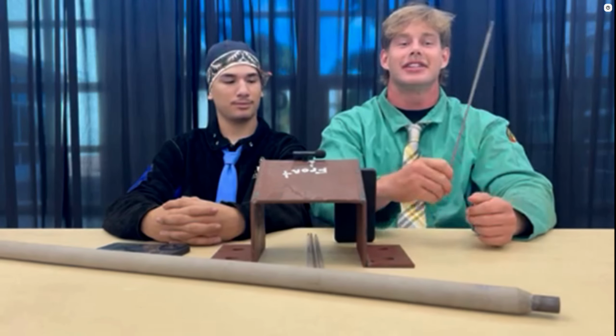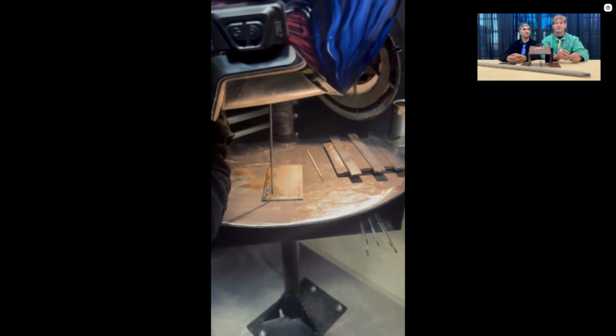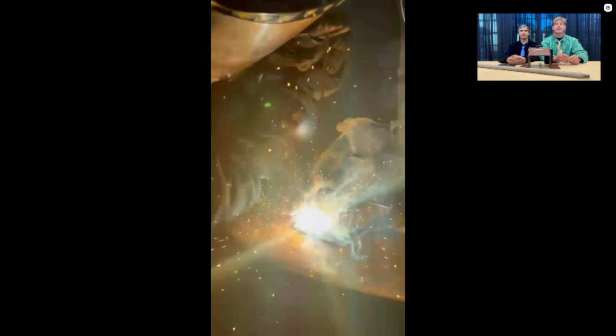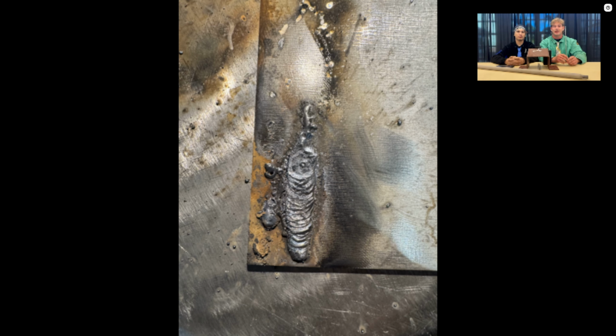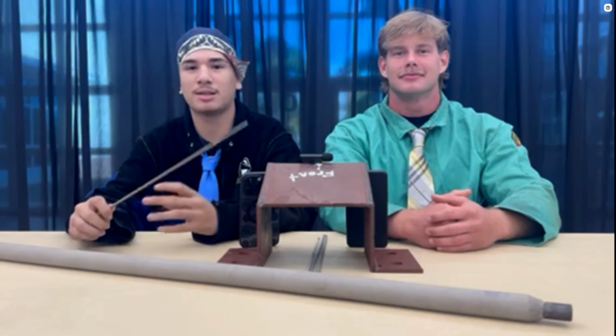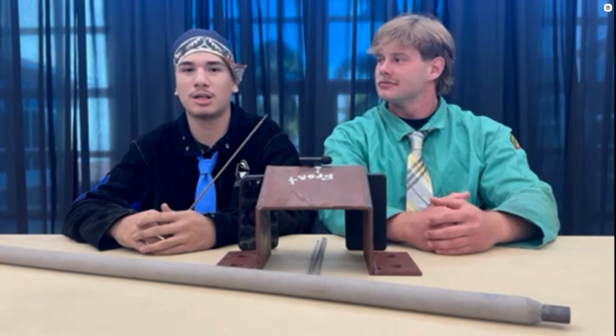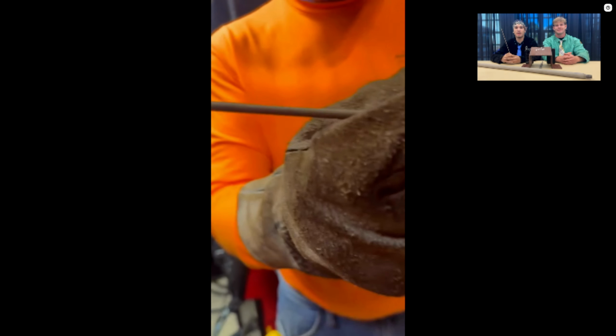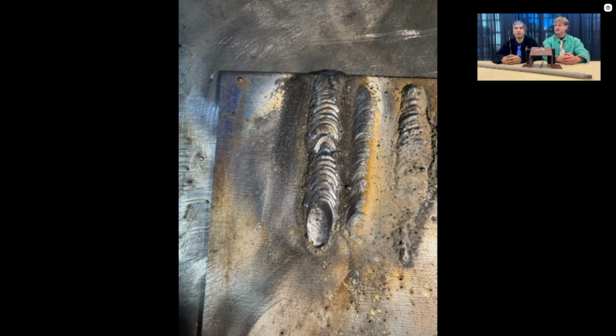Next on the list is our 6010 electrode. This is deep penetration, which makes it really good for welding dirty, rusty, and thick material. It's a standard for pipe welding root passes. The disadvantages are that it's challenging for beginners because of the aggressive arc and it's only DC power source. 6011 is almost a close counterpart to 6010, but it can be used with AC and DC power units, which makes it very versatile. But unlike its stepbrother, it has a very rough weld appearance.